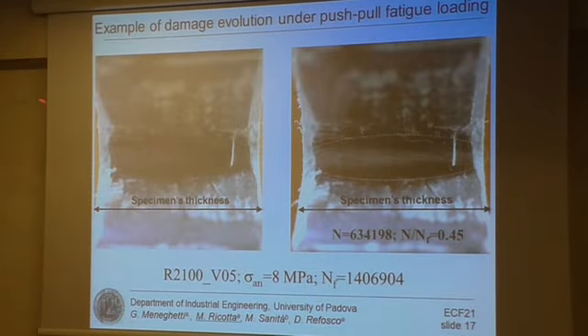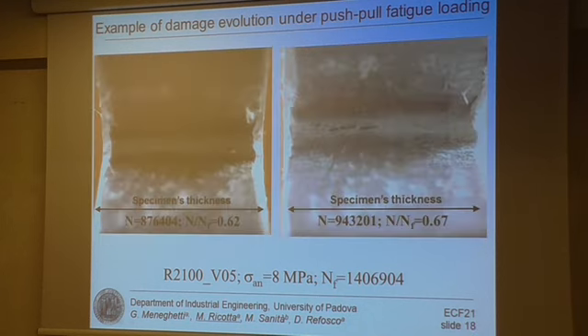Just an example of damage evolution observed in the case of fatigue load. Here we can see the specimen thickness, therefore we are seeing the specimen from lateral view. Here we are inside the notch, in the case of totally recycled polypropylene and high cycle fatigue. This is the initial condition of the material. Here we can see the damage that is characterized by material whitening, as you can find in literature, at 45% of total fatigue life. This whitening grows in the thickness direction.